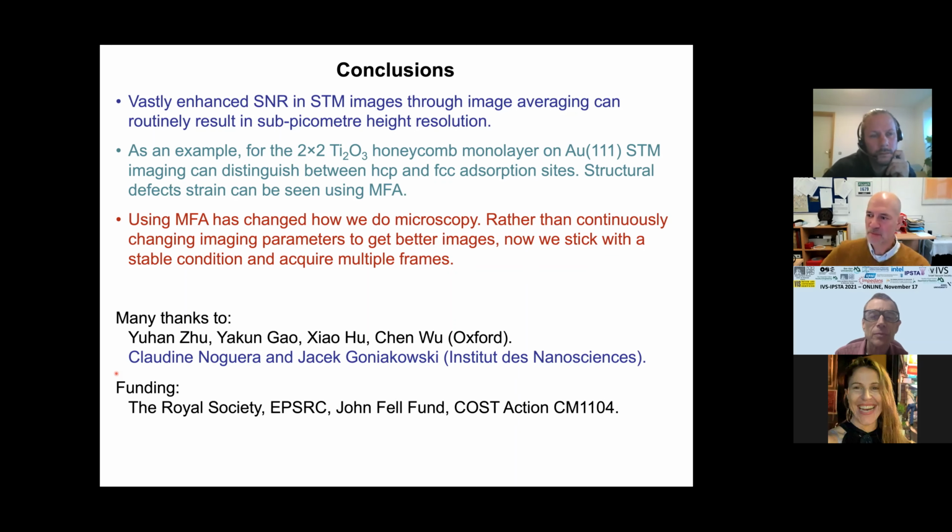Yeah, so this is Philip Moriarty, who I know, who's at the University of Nottingham. He does this as well. And their approach is, as you know, the more STM images you take, or the more AFM images you take, the more likely you are to get a nice result, right? So what they do is they run it overnight, and then they have most of it junk, of course. So they have a neural network to figure out, is it an image that's worth having or not?